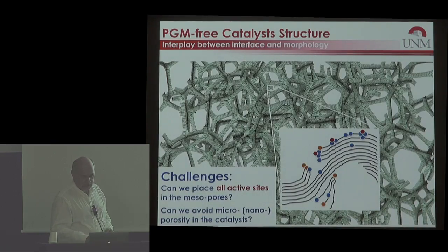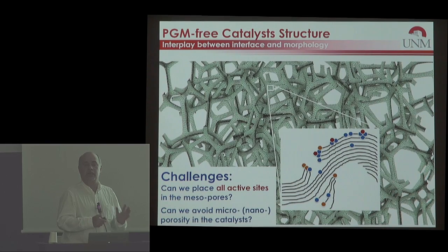The mental image is that the material that we produce is an open frame structure, carbonaceous material, relatively graphitic in content, but with a high level of disorder, and it has two types of defects: the in-plane defects, described to you by Frederick, and the edge defects. They both coexist. And we don't know which defects are more reactive and which defects are more stable. Just generically, we can suggest that in-plane defects are probably more stable than edge defects, but this is from general considerations.